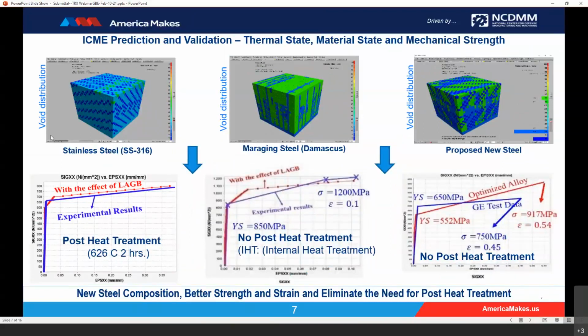ICME prediction and validation of the thermal state, material state, and mechanical strength. Recall the void distribution between the three states, which was a function of fused and unfused powders, and the effect of precipitates and inclusions. Not surprisingly, the same components impact the stress-strain curves for all three systems.